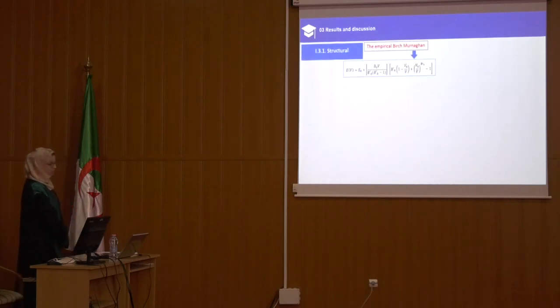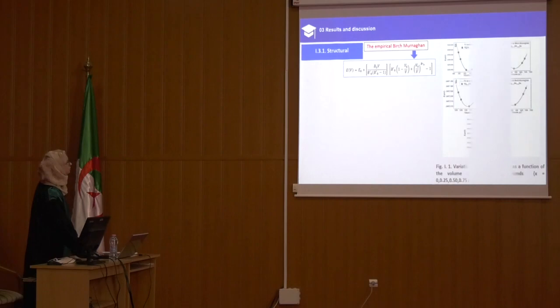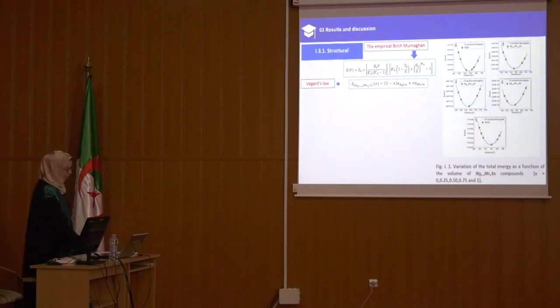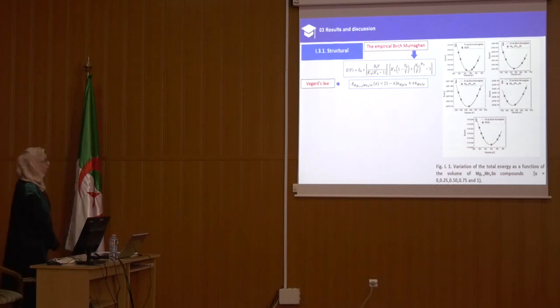For the structural properties, first we calculate the lattice parameter for each concentration using Vegard's law as input parameter. Then we minimize the total energy with respect to volume and fit it with the empirical Birch-Murnaghan equation of state to obtain the ground state structural properties.